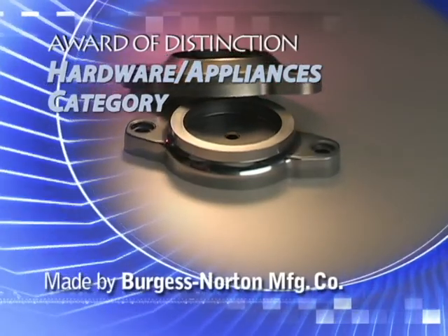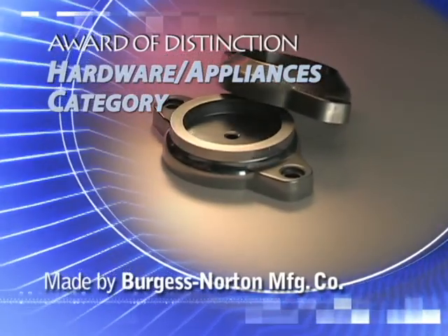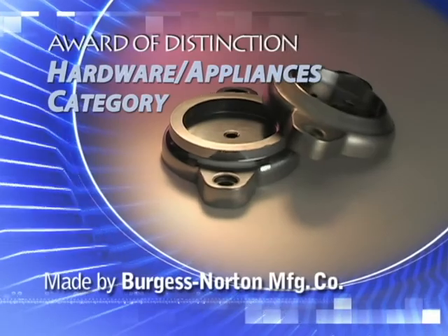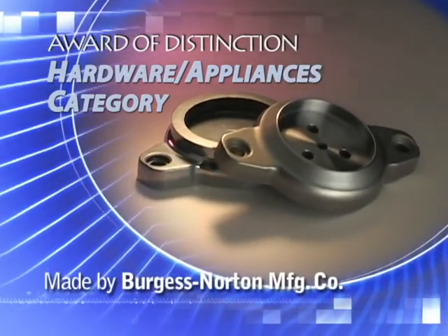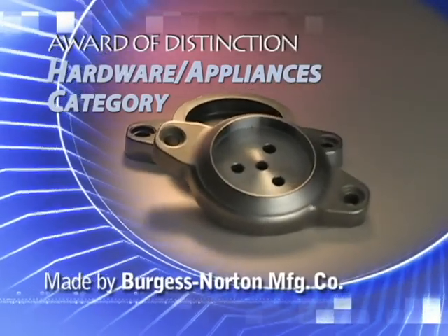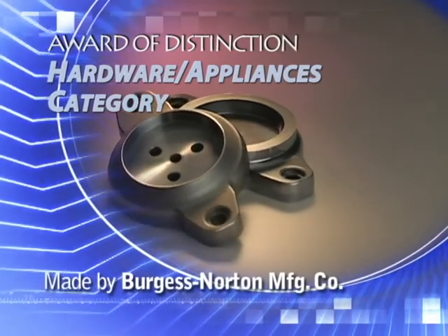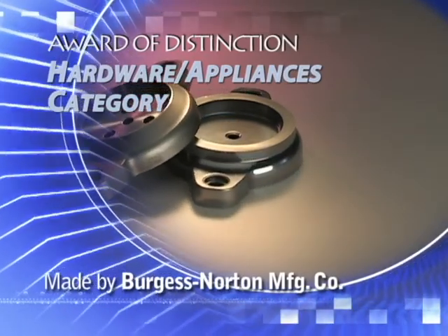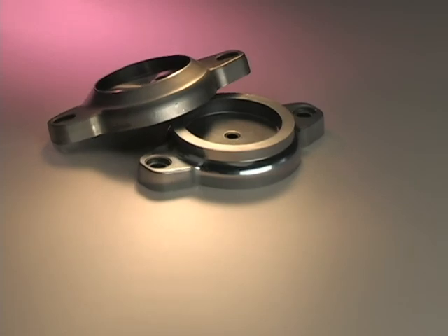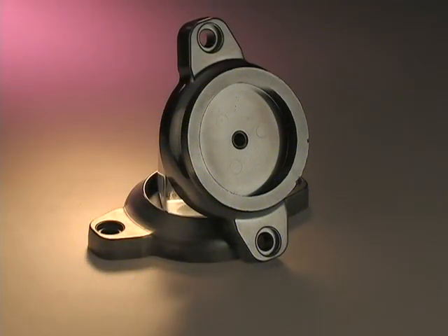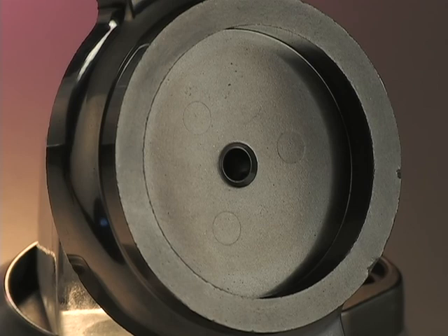Burgess Norton Manufacturing Company has earned an award of distinction in the hardware appliances category for a PM steel crimp retainer operating in a valve that regulates gas flow in a high-performance compressor for commercial refrigerators. Formed to a minimum density of 7.1 grams per cubic centimeter, the part has a minimum ultimate tensile strength of 160,000 psi, a yield strength of 150,000 psi, and 74 HRA hardness.